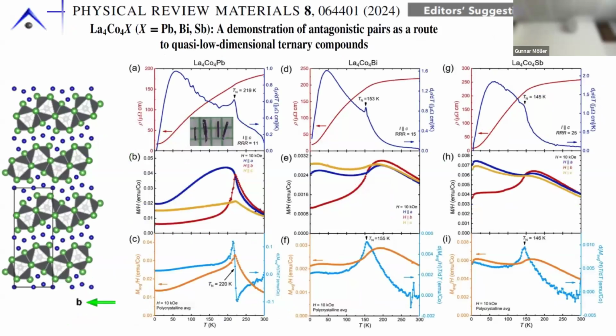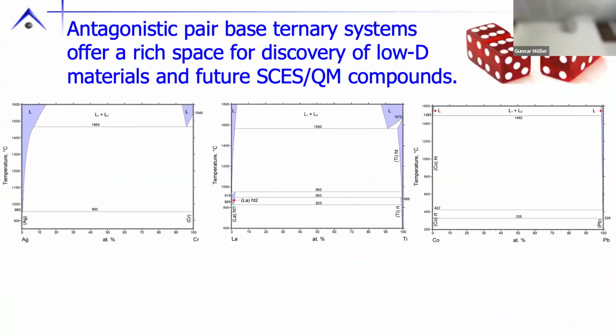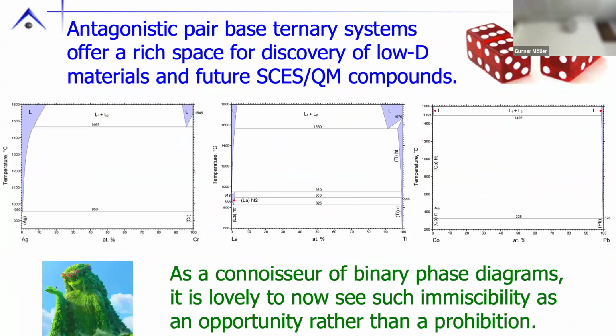And it's not just one material. We could find it for lead, bismuth, antimony. We have indications of tin. And they're all moment bearing. And they show, again, hints of low-dimensional magnetic ordering. So this is a beautiful recipe for dialing in dimensionality. And we've continued to look at this. We've found at least 4 other examples of new crystal structures that are antagonistic pair based and have low dimensional motifs. So this is very, very intriguing. And as a connoisseur of binary phase diagrams, it's nice to see these phase diagrams that in the old days turned the page, nothing here, turned into, whoa, that's an opportunity. Maybe I can create a new low dimensional material for study.